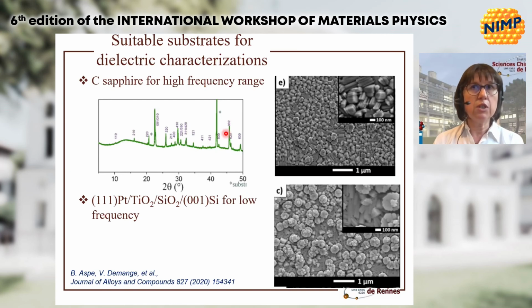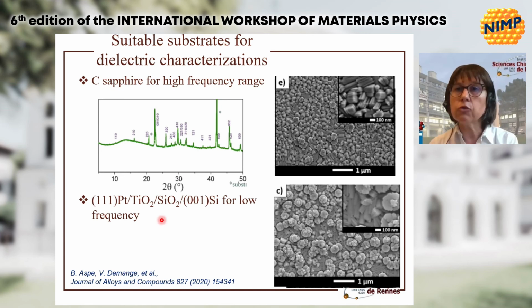Pure phase of TTB has been obtained with this type of microstructure, corresponding to the different orientations that have been observed. Some additional films have been deposited on platinum-coated silicon for low-frequency dielectric measurements.